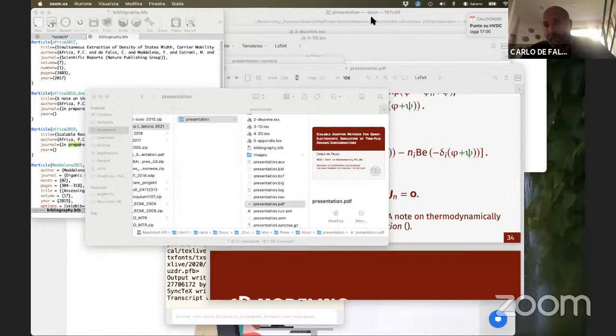It's not a huge number, but as the problem is highly nonlinear, we really need to do a lot of computation. I know of much higher simulations with a much higher number of degrees of freedom, but the nonlinearity in this case matters, and also the time stepping. I haven't discussed this topic, but the time scale of the simulations can be down to the picosecond, and so simulating milliseconds or seconds is non-trivial. So even just 30 million nodes requires a lot of computation.